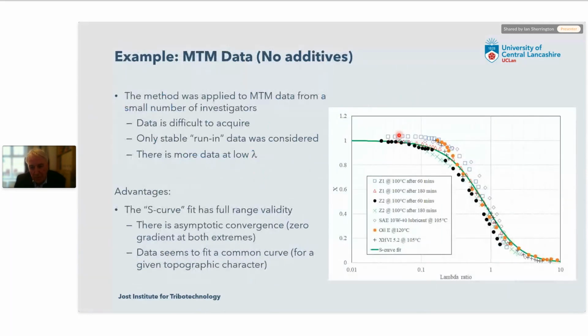Here's our evidence. So these data points in this graph are placed on a graph like the one I mentioned. Lambda ratio across the x-axis and the ratio of mixed to boundary lubrication on the y-axis. All of these data points are taken from published data. So this is not our own data. This is data that we've collected from other publishers. And we did notice straight away it's quite difficult to acquire.